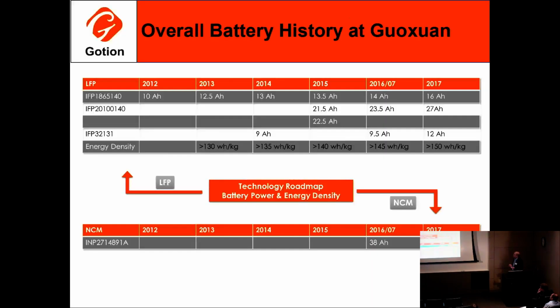So where are we headed? Here's where we are, from the beginning of making cells in 2012 to where we are today in 2017. Again, mostly focused on LFP, going from 10 amp hours up to 16 amp hours and 27 amp hours, depending on the shape and size of the cell. And you can see the energy density has gone up from 130 to 150 watt hours per kilogram.